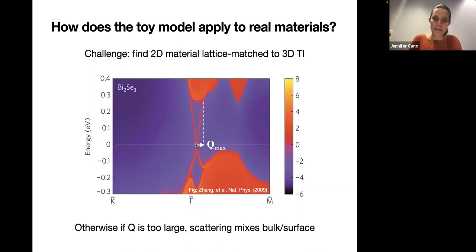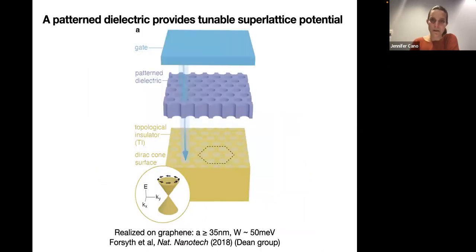So the basic problem is that if your mismatch is too big, then the resulting wave vector Q of the moire pattern is going to be too big, and you're going to start coupling surface states to bulk states, and that's going to have some very different physics. So we want to keep that wave vector very small so that we can just couple the surface states. And so that led us to this alternate approach that I was talking about.